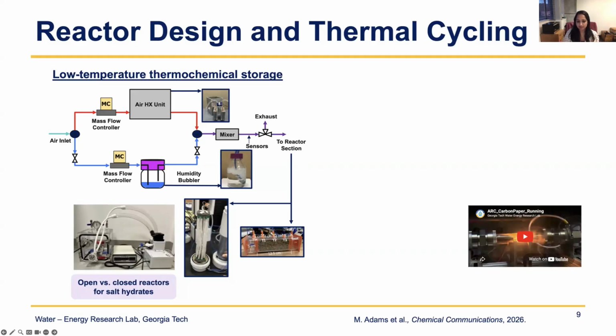This is about 100 grams of material that we test with thermocouples in order to measure how much temperature increase we get, or temperature lift, as well as how much power we can generate, thermal power output from these different types of reactors. So packed bed, as well as some fiber-based shell and tube geometries, and then also some cycling of the material under very controlled environments.